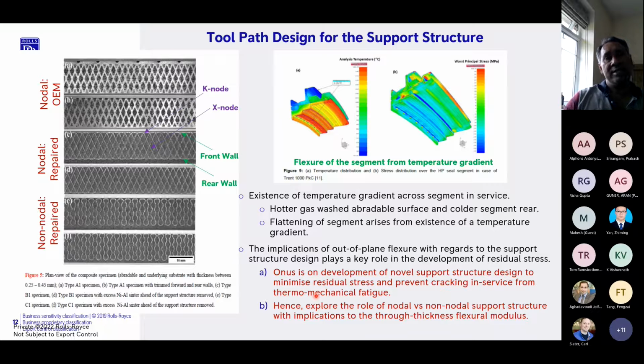What kind of tests do we need to do to assess different designs? It's not straightforward to do any form of diffraction-based work to look at residual stresses, because these materials are highly textured and they're not entirely metallic. You've got a metallic support structure, but in between it you've got a sinter filler, say nickel aluminide, which also gets basically oxidized. So we must find a test that we can use quite reliably to qualify different support structure designs.